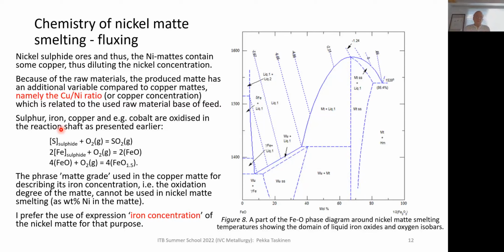High concentrations here mean certain large volume concentrates available from Canada and Russia, where the copper to nickel weight ratio is typically 1:2 or 1:3.